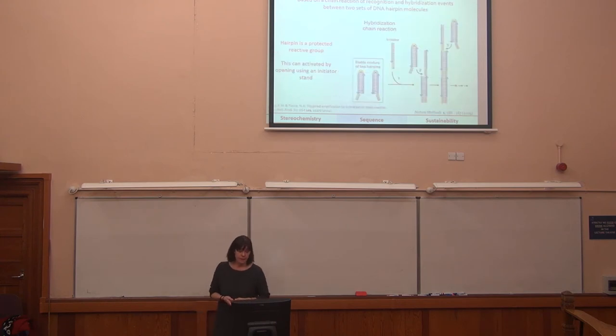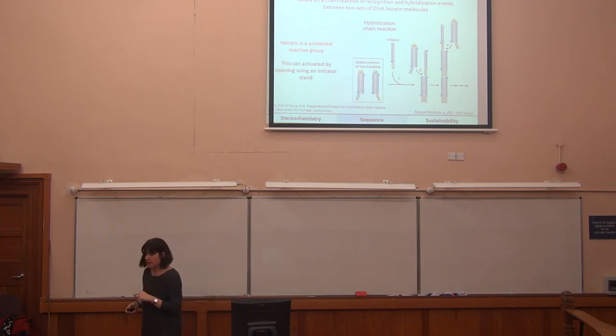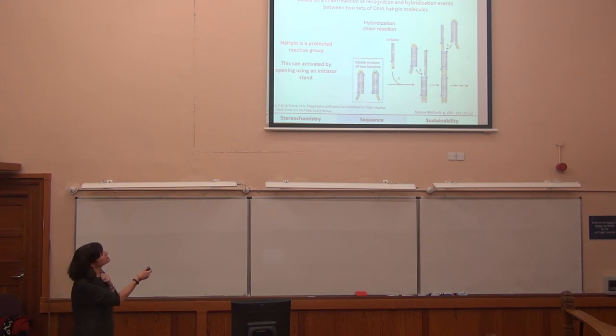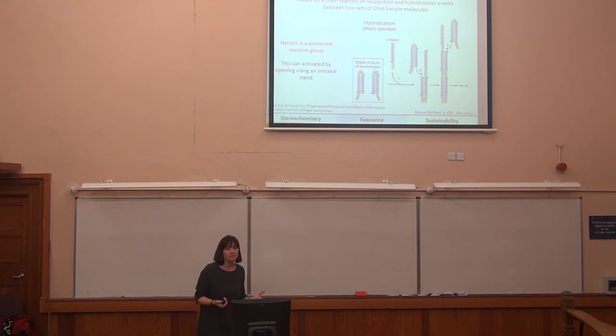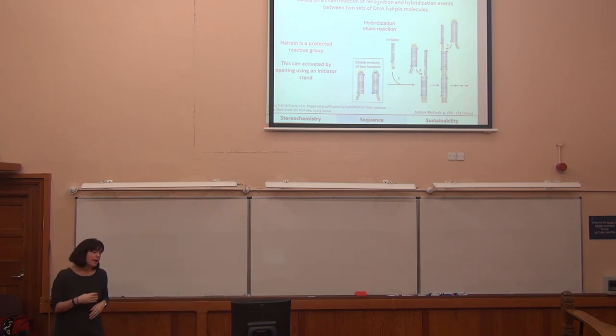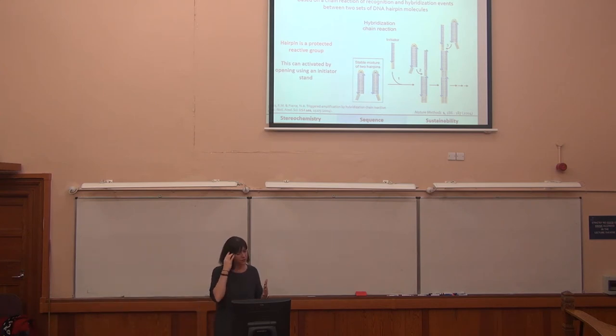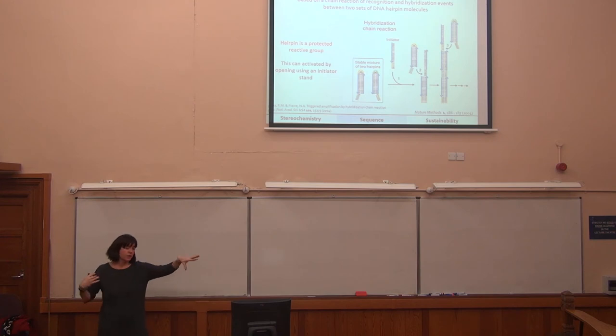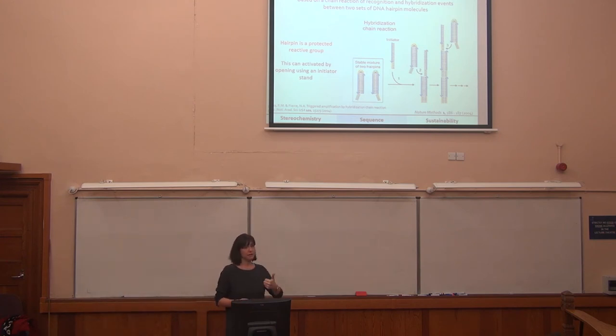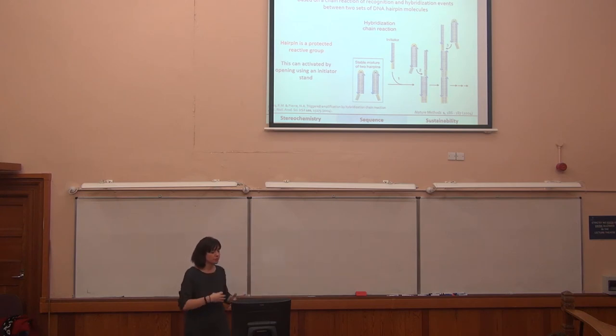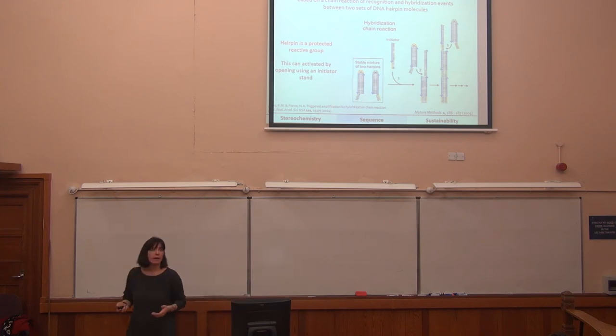And this is very much inspired by this work from Niles Pierce on the HCR reaction. And as a polymer scientist, this is amazing. You basically store potential energy in the loops, and you have an initiator strand that kicks off and starts the process. So you imagine you have two stable hairpins. You have an initiator that opens one of these hairpins, and as you open that hairpin, you expose the green DNA strand, and then you have the complementary hairpin toehold that can hybridize. This reaction allows for an autonomous growth and production of this duplex. So essentially you have an initiator that kicks off your polymerization, and you have potential energy stored in your hairpins to allow you to get this growth of a duplex.